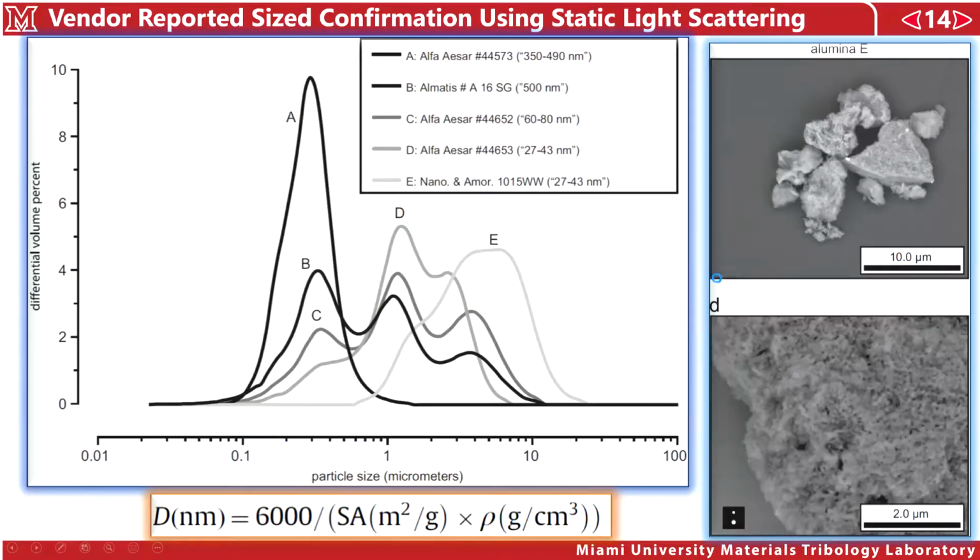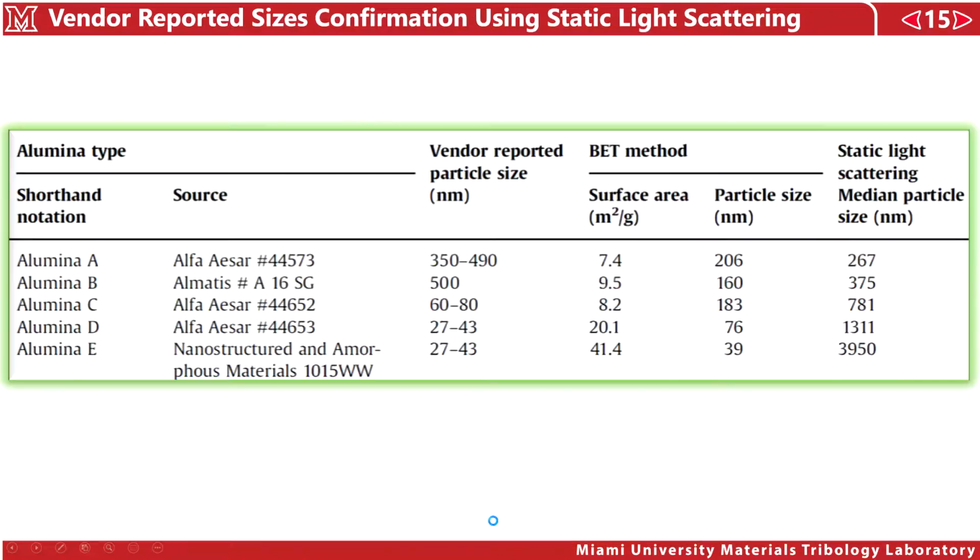This image tells the story. The porosity is an important factor. This equation can be used only if certain assumptions are met, and in the assumptions, the particles have to be dense and non-porous, whereas here clearly the particles are porous, and therefore this equation cannot be used to estimate the size of the particles.